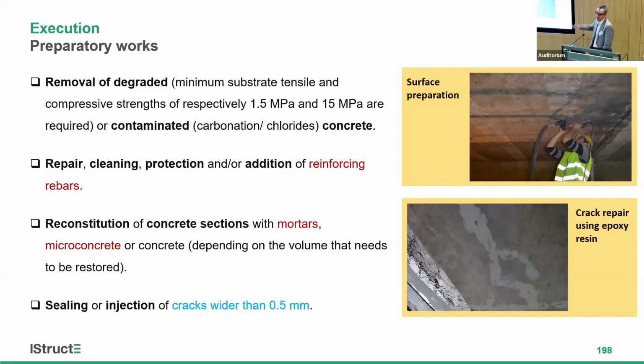Otherwise, corrosion will come later. So we have to avoid this. In many cases, we have to repair, clean, protect, and sometimes add bars to replace the corroded ones. Typically, there is a suggestion that every time we face more than 10% reduction of the cross-section, we should replace it with a new bar.